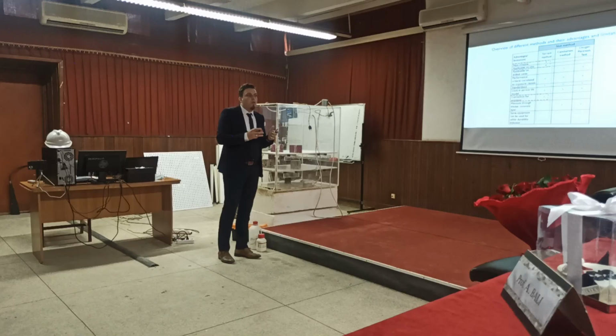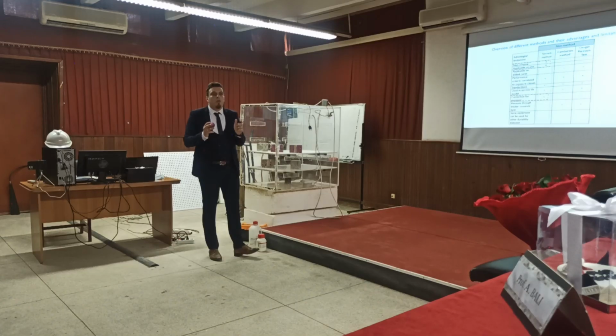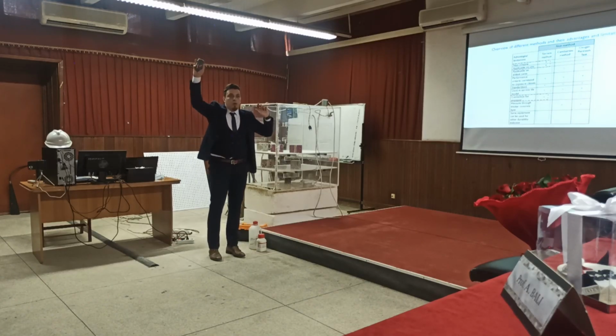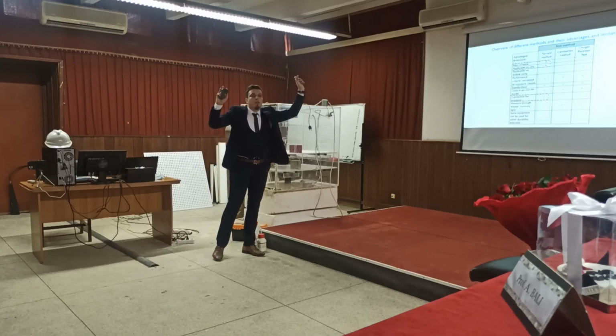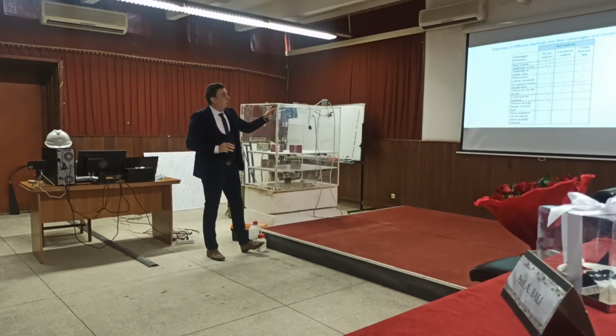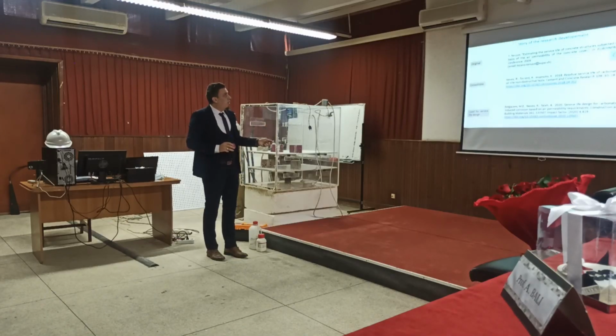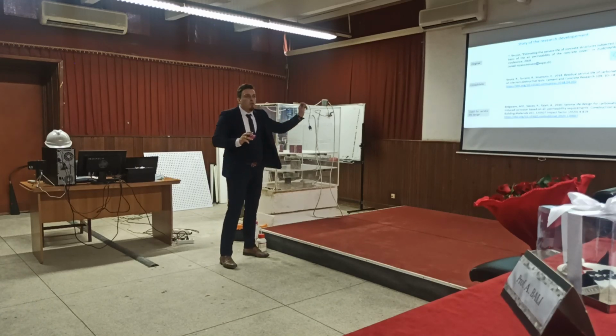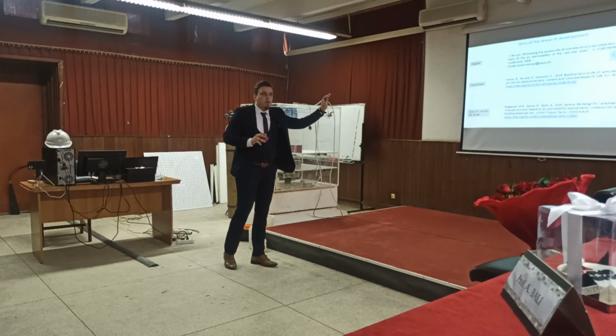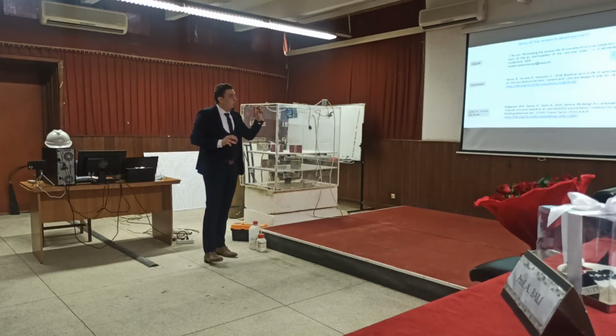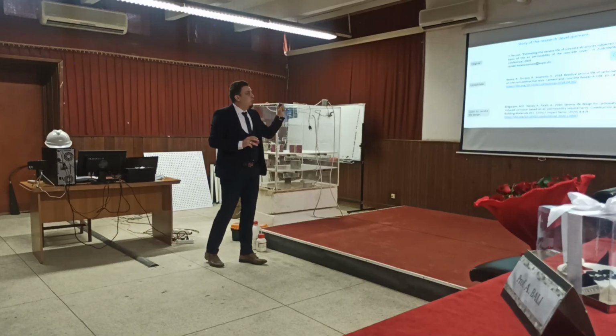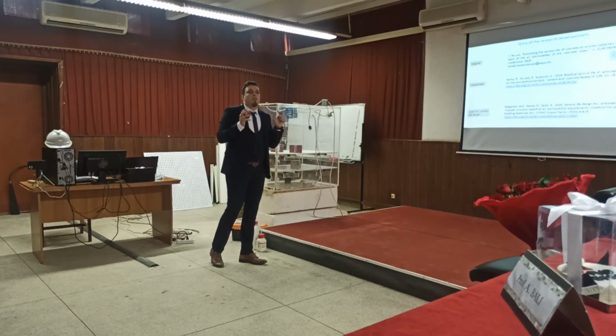So we searched for data with this method, and we found something interesting. We found that there is already a relationship between Torrent permeability and accelerated carbonation. The story of our research started in 2009 with the original work of Torrent. After that, the same approach was used by Neves in order to predict the residual service life. After that, we used the same approach in our research in order to predict the service life at the design stage.